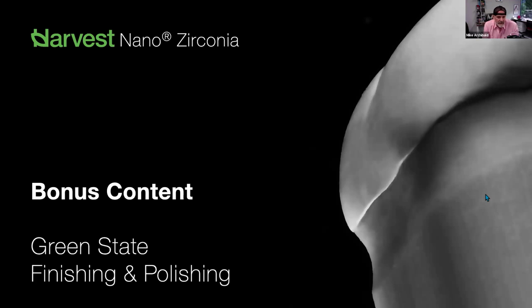But also our glazed materials and things like that. Glazed materials are porous, and when people grind into them, now we've exposed porosities within the material that doesn't get back to a polished state. And so acids in the mouth and things like lemon juice, Diet Coke, things like that, within months' time start eating that surface away, and we get down to whatever the raw core material was. And if it's rough, then we have a rough material, rough surface.